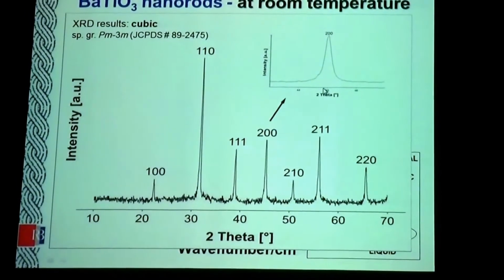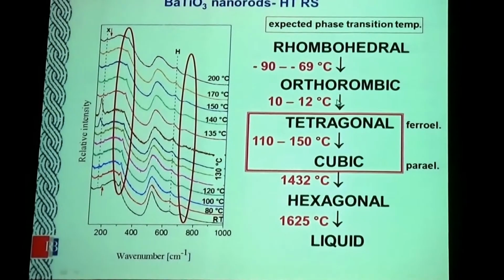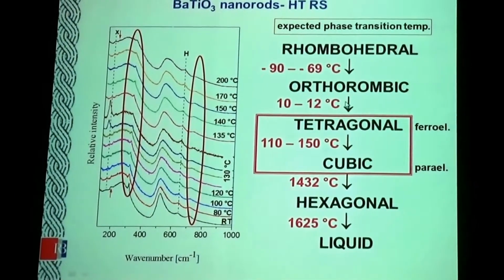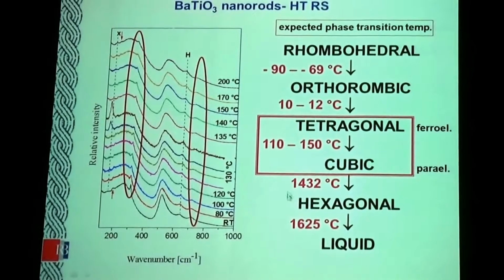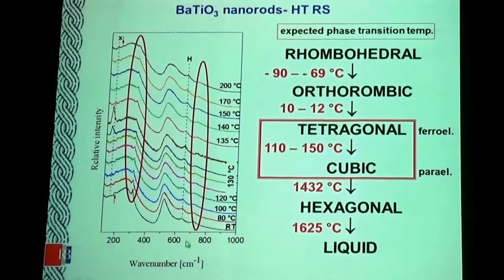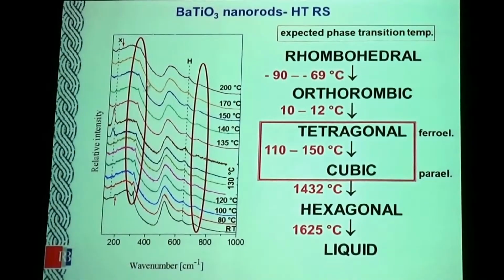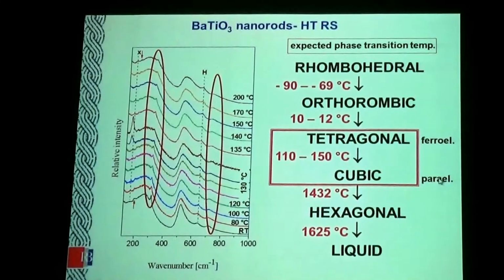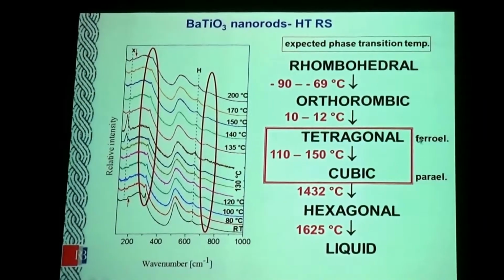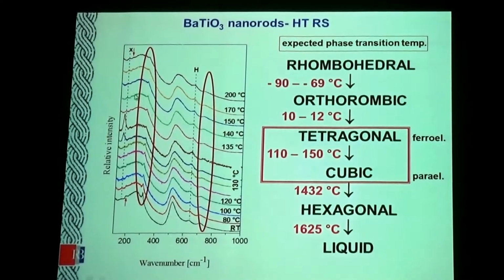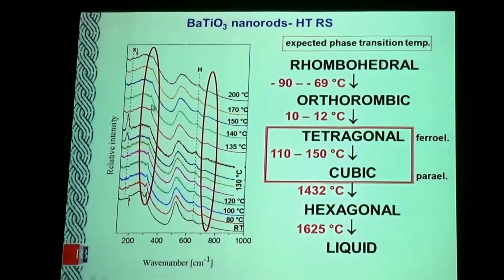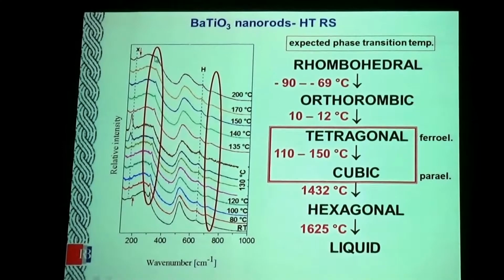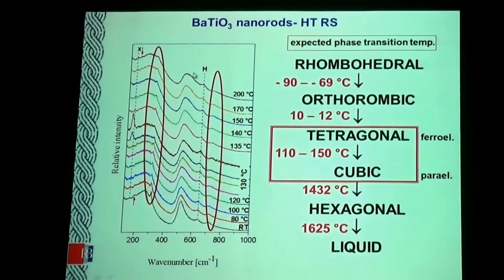So in such a system, Raman spectroscopy was shown to be a better method of choice for such a study. We also studied the most important phase transition in barium titanate, from ferroelectric to paraelectric state, and observed that the tetragonality still exists at much higher temperature than expected.